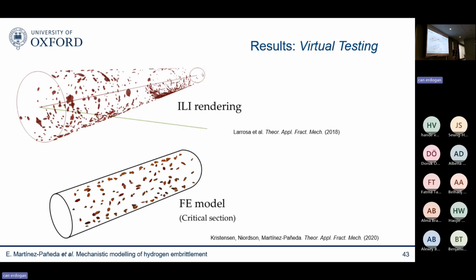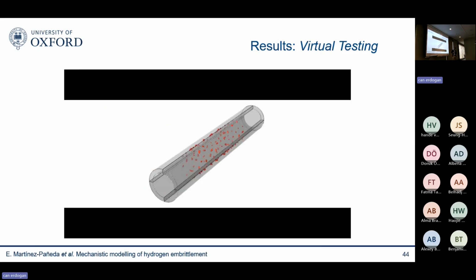For example, what you see here is a pipeline that contains hundreds of defects, which represent corrosion. All of those red dots are defects. We can easily incorporate those defects into our fundamental model because we are solving for the phase field as a degree of freedom. So you can just initialize your phase field equal to 1, and then you can simulate what happens. You can subject that pipeline to in-service conditions, and you can see how those defects are growing, how they merge with each other, and how eventually you get the complete failure of the pipeline.